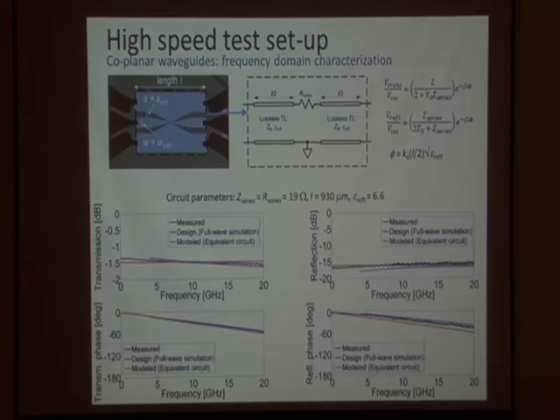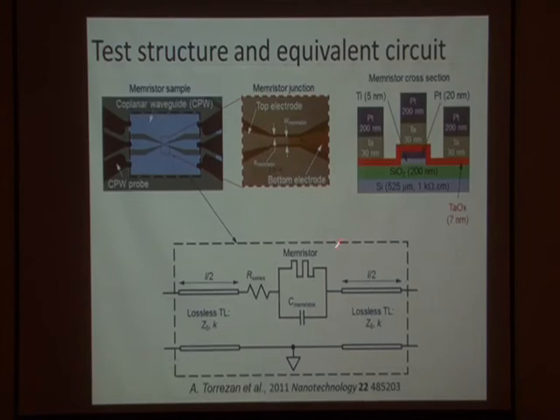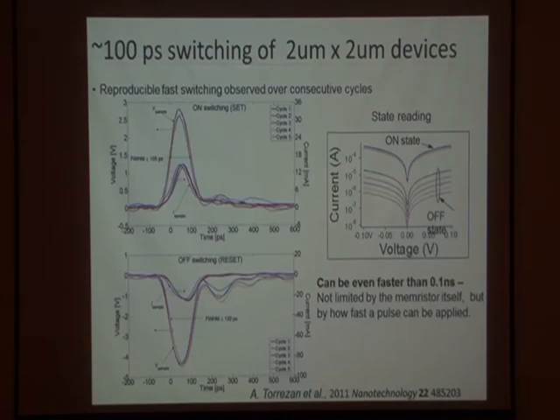So now that he understands this setup, because it's basically a setup, first he did it without the sample, the device. Then he's going to insert the device. This procedure is called the de-embedding procedure, and he's just a master at that. So now it's time to insert your sample in here, and here it is. Now that he knows everything around your device, you can actually measure with precision the amplitude of the signal across your device and the time. So you can measure everything for sure, and not with a regular probe station.